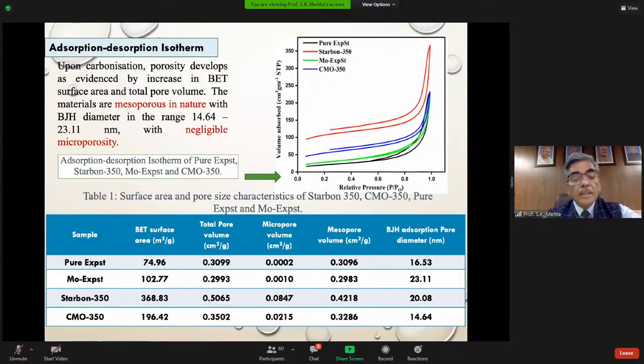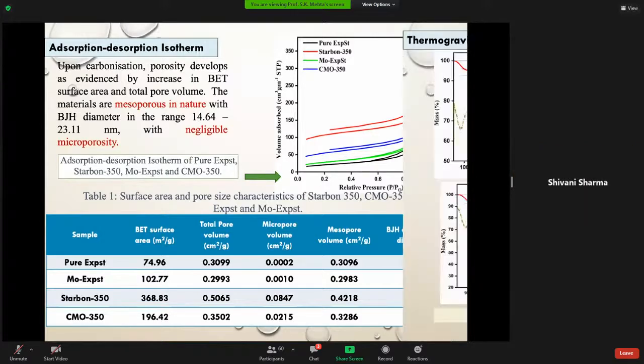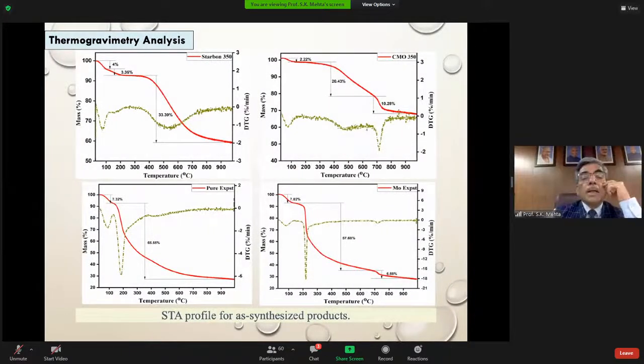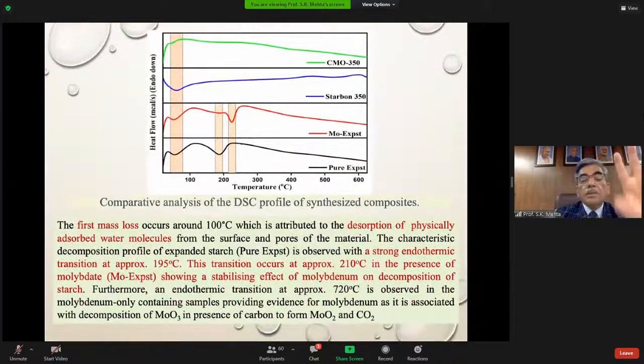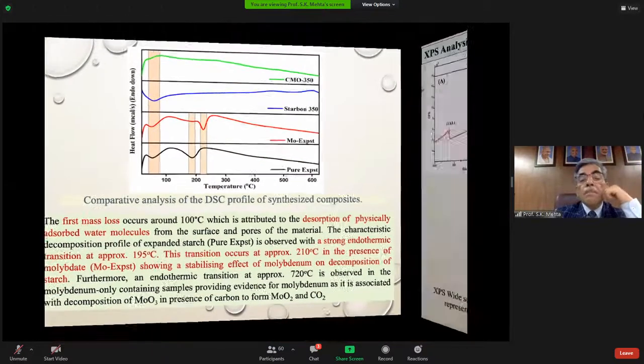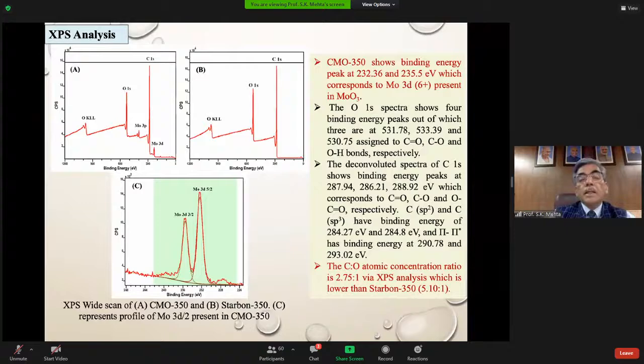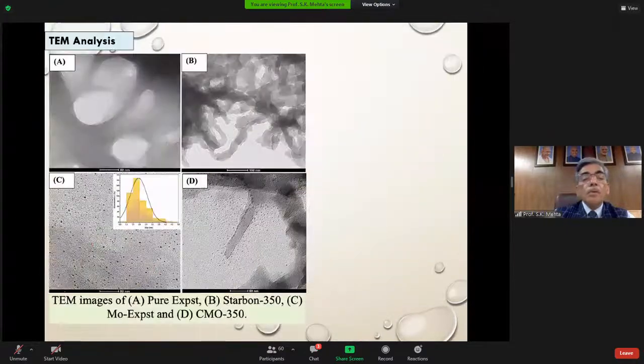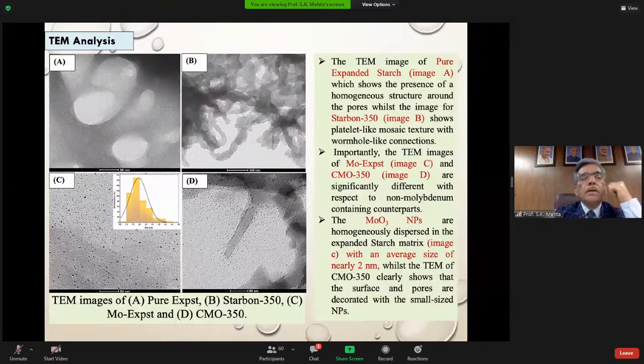So you can see from pure to molybdenum based, there is an increase in the BET surface area, and starbon also has a high surface area, 368 meters squared per gram. CMO is also 196. Now this is the thermogravimetric analysis, and this is the comparative analysis we have done. Then XPS analysis was done. So all the characterization needed for characterizing new materials was also done.